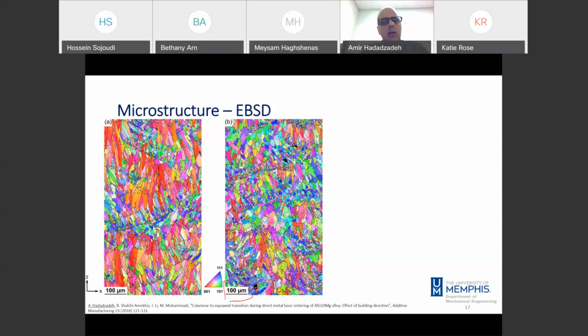The grain structure of both samples, more or less, consists of columnar grains. So these grains, as you see here, are columnar grains. They have developed along the building direction because of the direction of the heat transfer. In the horizontal sample, we also have the same thing. On the left-hand side, we have the vertical sample. Here on the right, we have the horizontal sample. More or less, we have kind of a bimodal grain structure, both equiaxed and columnar structures.